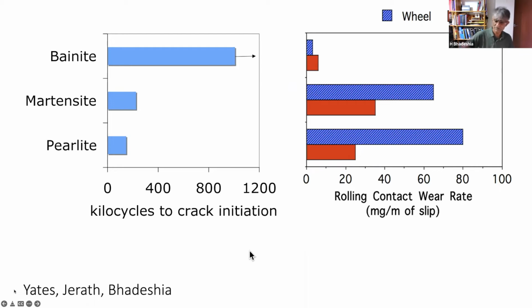And the second thing is, if you press on a surface, a sphere on a surface, you actually induce a large shear stress under the surface. So every time a wheel goes over the surface, you get a cycle of shear stress under the surface, and that eventually leads to fatigue and a flaking off of material. So these are full-scale tests which were done in Poland, and you can see that our material outperformed anything that exists, and we stopped the test because we were being charged quite a lot for these tests.